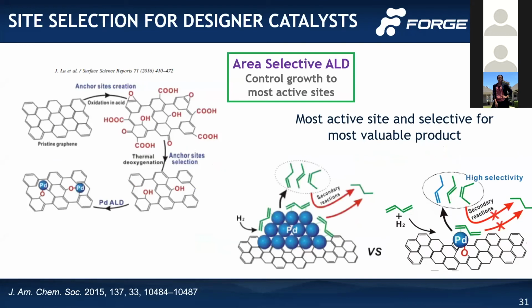The area selective deposition was in the review paper, and here's the reference to the original work. This takes pristine graphene, makes some oxide sites, then deposits palladium onto those specific sites, so you can get almost a single site palladium reaction. The opportunity here is high selectivity - you can get high yield to a single desired product and eliminate secondary reactions in your stream, improving overall process economics and potentially creating an opportunity for commercialization.